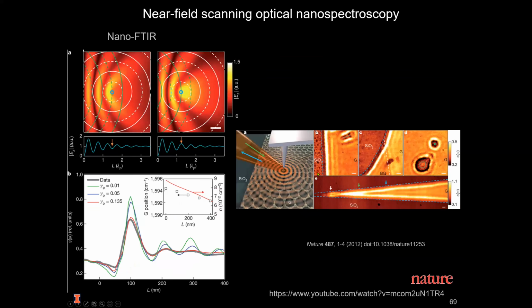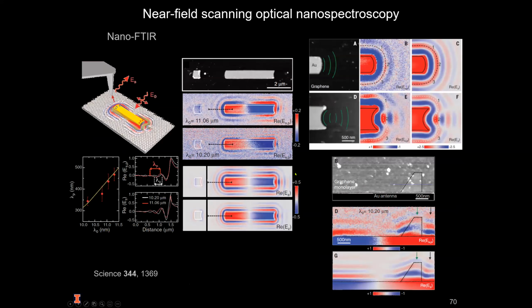Another example of SNOM application for characterizing nanomaterials is the study of plasmons on graphene, either generated by the microscope tip itself, as in this work here, where the reflections of those plasmons launched by the tip by the edges of the graphene flakes were measured, or generated by the interaction of an antenna on the sample and the incident light, and then measured by the metallic tip.